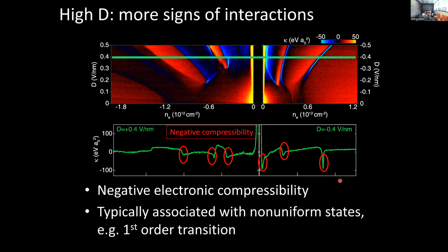But all of this gets much more dramatic once you put in a large displacement field, which, if you'll recall, is really equivalent to making this density of states very large, because that piles up density of states right near this band edge. And now we see a bunch of things that are very clearly coming from symmetry breaking. In particular, one of the features you see is these strong negative compressibility features, where the compressibility, which is really just inverse density of states in a single particle picture, becomes negative.